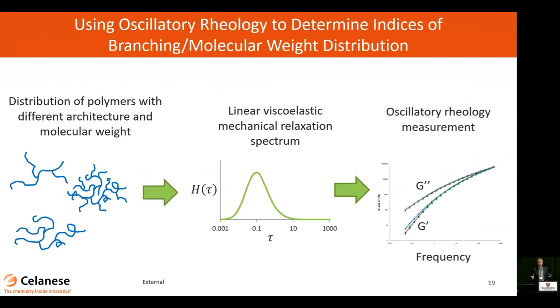So if we have a complex mixture of polymers that are polydispersed with varying degrees of long chain branching, any mixture of polymers will produce some linear viscoelastic mechanical relaxation spectrum in some sort of linear viscoelastic measurement. And any spectrum of linear viscoelastic relaxation times will in turn produce linear viscoelastic measurement data, like an oscillatory rheology measurement where you measure storage and loss modulus as a function of frequency. So what we'd like to do is use that oscillatory rheology measurement to infer things about the breadth of this mechanical relaxation spectrum. And then if we can compare things about the breadth of that relaxation spectrum, that gives us a basis for comparing different polymers.